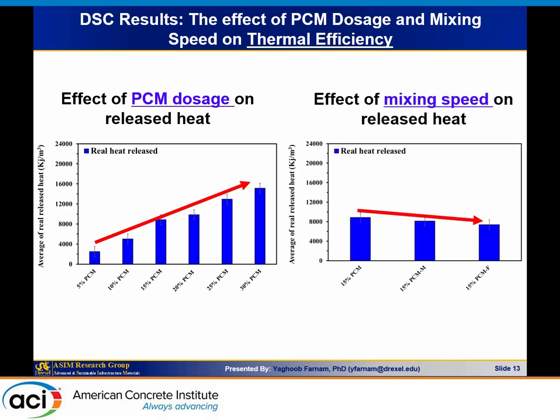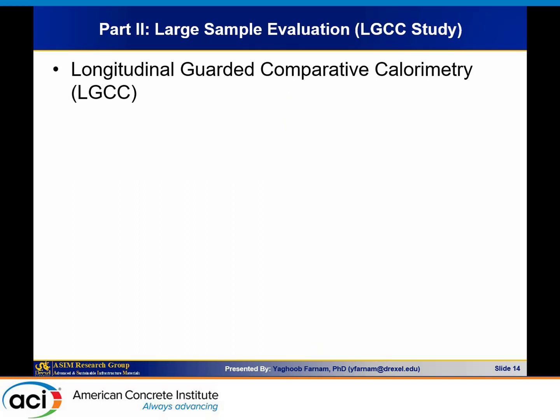And effect of mixing speed: as we increase the mixing speed, we have lots of friction, and we could actually break our PCM. And this is what type of behavior? Linear reduction inside our sample. So this is something that we have to be very careful about. The amount of mixing, the time of mixing, the speed of mixing, these are the things that we have to be very careful about.